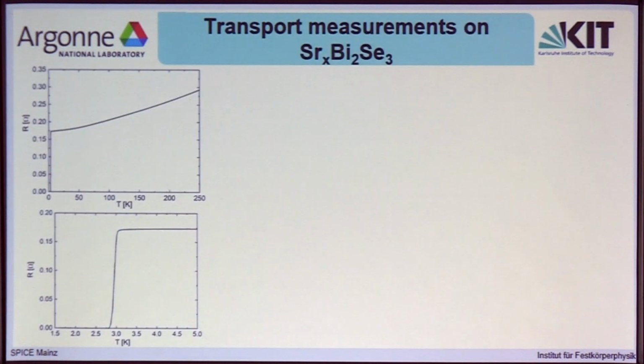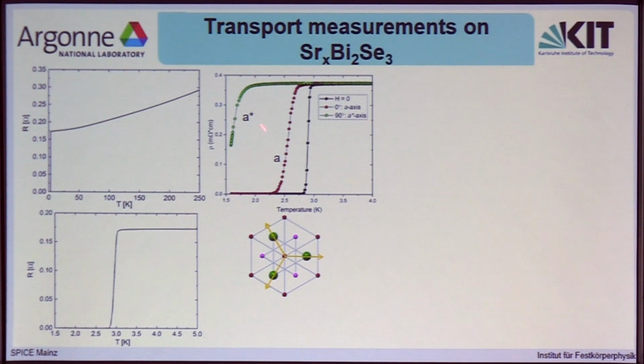So the first one is actually the same transport measurement that we have done before. However, now we've oriented our crystal beforehand with X-ray diffraction so that we know which way the A-axis and the A-star axis in our transport sample are actually pointing. And if we apply a field of 1 Tesla along the A-axis or the A-star axis, we actually see which one has the maximum HC2 and which one has the minimum HC2. And obviously, the one which has the minimum HC2 also has to have the minimum in the superconducting gap structure. And this one has to have the larger gap.